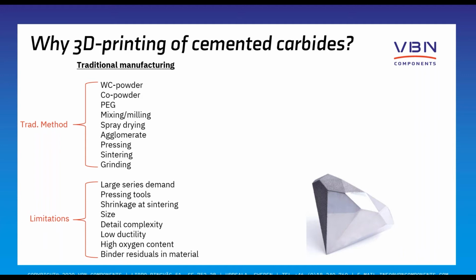And typically you have a problem in the brittleness of the material, and you also have a problem in the complexity. It's difficult to have a complex shape when you need pressing tools and green bodies and sintering. And also you need the large series. It's very difficult to make 1 or 2 or 10 of something when you need to do thousands of them to get the good in the long run.